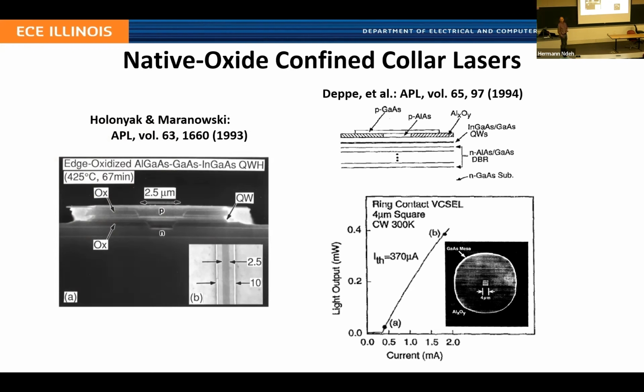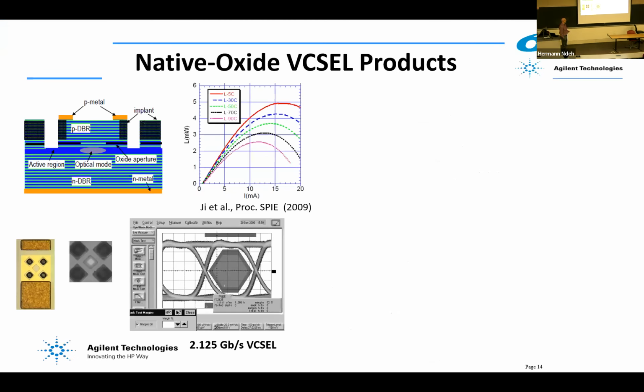emitting laser. And so with the oxide technology came the ability to make the lowest threshold and highest efficiency vertical cavity surface emitting lasers. And that has now become the dominant technology used in all the vertical cavity lasers out there. Well over 90% of all the lasers made use the native oxide for both index guiding and current confinement.